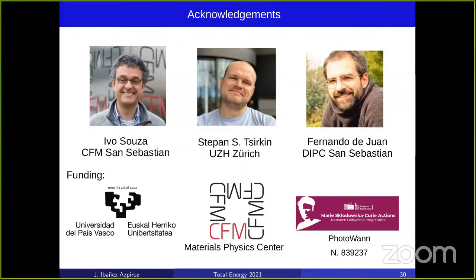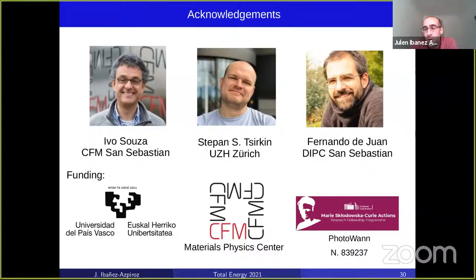Hello, am I audible? Yes. Thank you, Professor Julian, for the nice talk. I have a question: is spin orbit coupling necessary for doing the shift current calculations? Good question. It's not a key player, because the results I have shown are for semiconductors with a big band gap. Spin orbit coupling wouldn't play much of a role here. It's not like the anomalous Hall effect, where spin orbit coupling can be key; here the physics is not dictated by spin orbit coupling. It can matter in recently interesting materials for nonlinear phenomena, like Weyl semimetals, where the band gap is smaller and spin orbit coupling will have bigger effects.